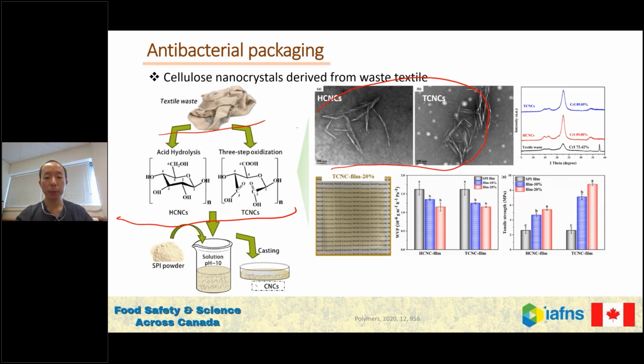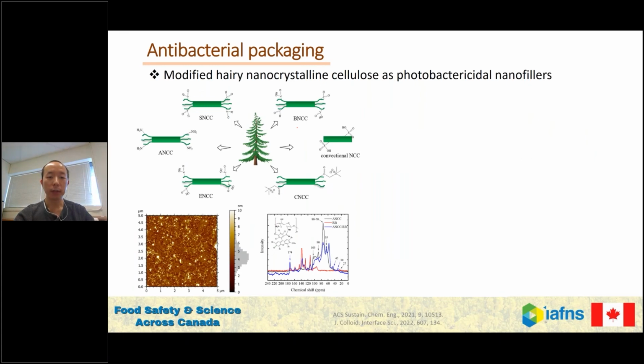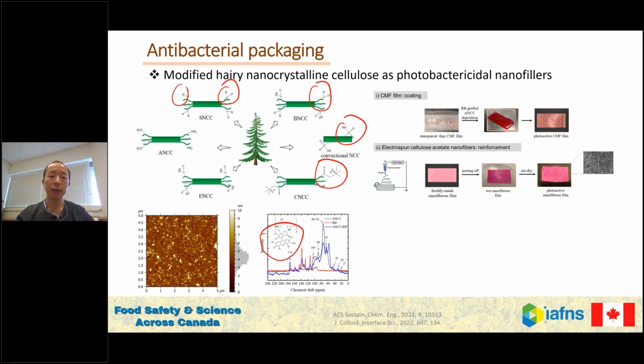So after that, what we can do, we can modify the surface of those nanocellulose. For example, we can have different functional groups on the nanocellulose. And after that, we can link compounds on those nanocellulose. For example, we use rose bengal, that's a natural compound, and it can generate ROS under the light. So we link rose bengal on our nanocellulose, and after that, it's a kind of nanofiller.